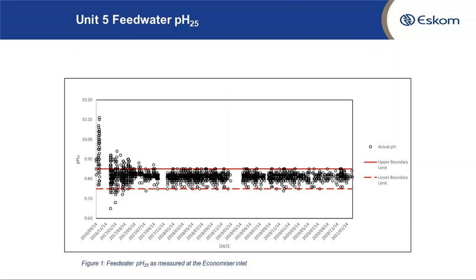If you look at during early operation, yes, the data include events such as steam blow through data. That is why you will see the pH way off the range, difficult to control. But as we started with the commissioning, we got better control of the pH, and then we started to operate well within the required pH range. This is basically to give you the background information in terms of the feed water and steam pH, because this is critical when we start assessing the chemistry of the ACC condensate. Next slide, Scott.